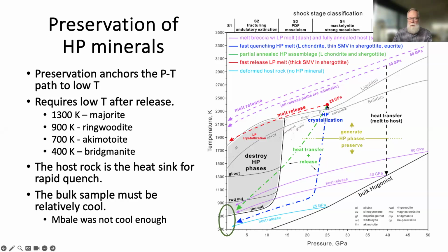I have this very hot melt in contact with a cool host, and the path is dominated by conduction of heat to the surrounding, right? And that dumps the heat out, drops the temperature, and then pressure release takes us down here. The exact path that we get depends on how much melt you have, where you are within the melt. The edge of the melt quench is much faster than the center, and so on. So we have actually an array of paths for a given sample. But what happens is these all bring us down in below here. So it's a system that's dominated by the quench, produced by being in contact with a relatively cool host.